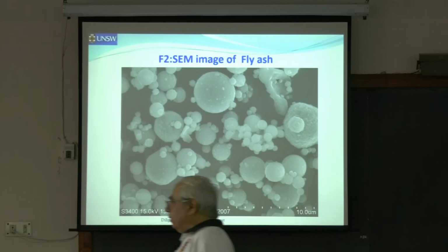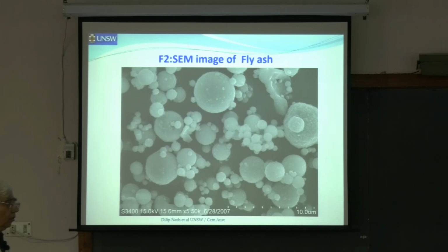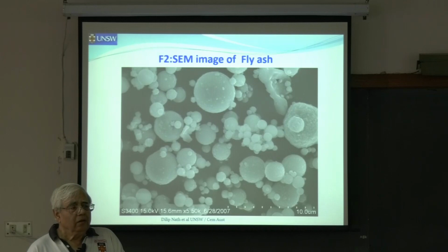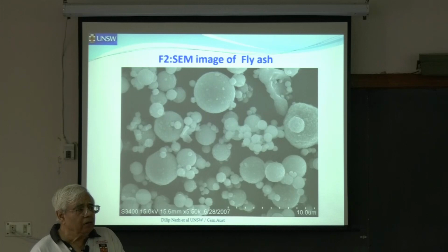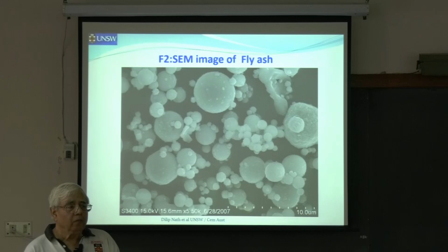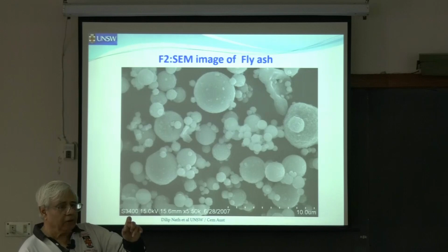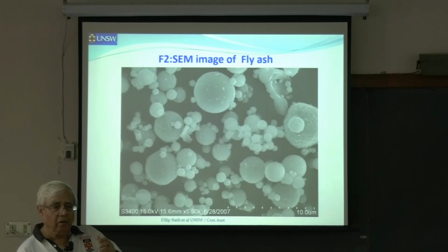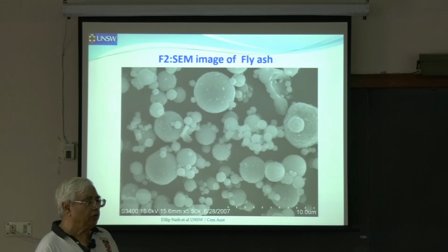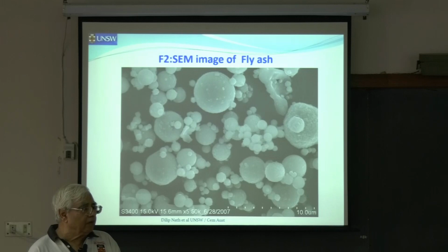And particle size distribution, in one of my latest research scholars' work, we find that it has some very good effect on dielectric properties. A certain range of particle size gives you the highest positive, the real, dielectric constant, and some other particle size distribution gives you the highest imaginary dielectric constant. So when the particle size changes like that, all of a sudden, this can have a valuable effect on those properties.